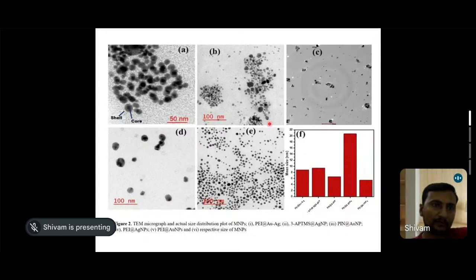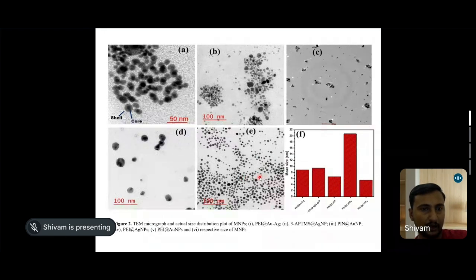Here is the TEM characterization. You can see the core-shell structure of the bimetallic nanoparticle. It is very clearly visible. Further, these are the different stabilized nanoparticles. Figure E demonstrates the PEI-stabilized gold nanoparticles. You can see that the nanoparticles are very well dispersed in comparison to B, the 3-APTMS-stabilized silver nanoparticles, and C, the polyindole-stabilized gold nanoparticles. PEI-stabilized gold nanoparticles were very well dispersed, with least chance of agglomeration.